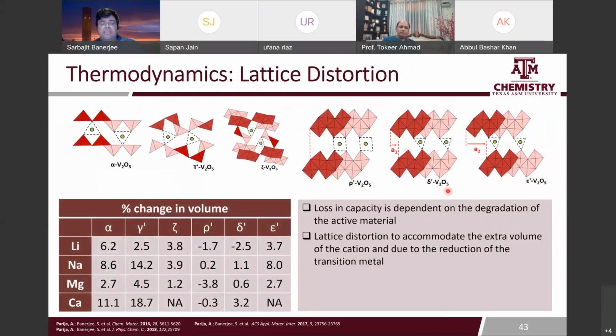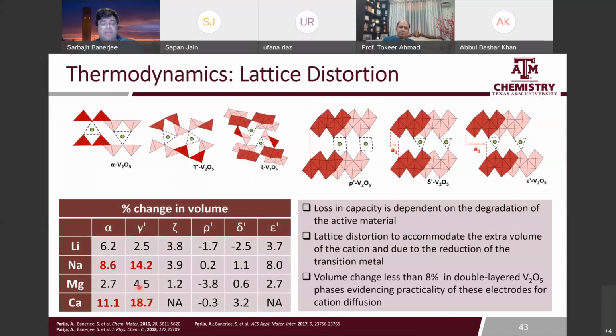Essentially, by looking at some of these other possibilities, you can identify a couple of other options for magnesium and calcium and such. And the change in volume, ideally based on the thermodynamics, should be low, because anytime you have a very large change in volume, degradation happens very quickly in these systems. So anything in red is really not ideal. Anything that has stayed black on my slide, these numbers are not large. Typically, you want a volume change less than 8%, right? And that's generally true with some exceptions.